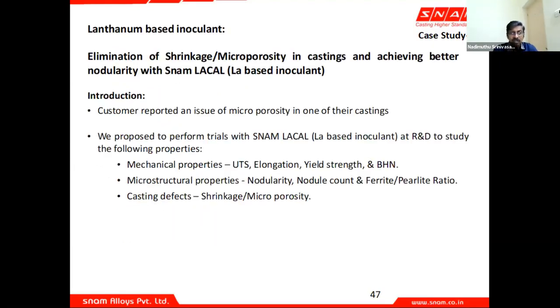Now next is a lanthanum based inoculant. So where lanthanum is used is in ductile iron, where you face a problem of shrinkage or microporosity. Now lanthanum is used in both, as I told you, in the magnesium alloy as well as in the inoculant. There is a higher percentage of lanthanum used in a typical magnesium alloy, like I had explained to you, LAMAC 3, where the lanthanum is in the range of 0.35 to 0.55 and magnesium is much more, 5.5 to 6%. So you can use lanthanum in both cases. So we will see how lanthanum can be used as an inoculant.